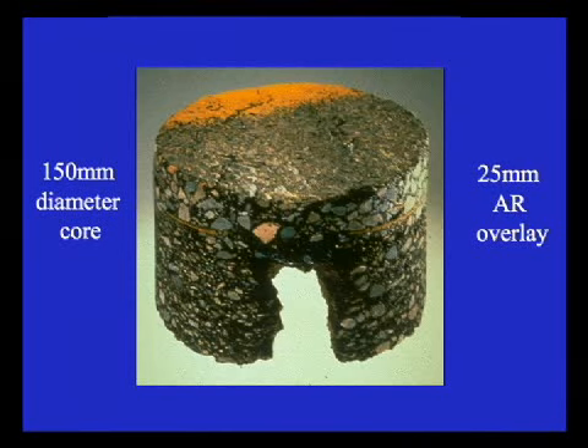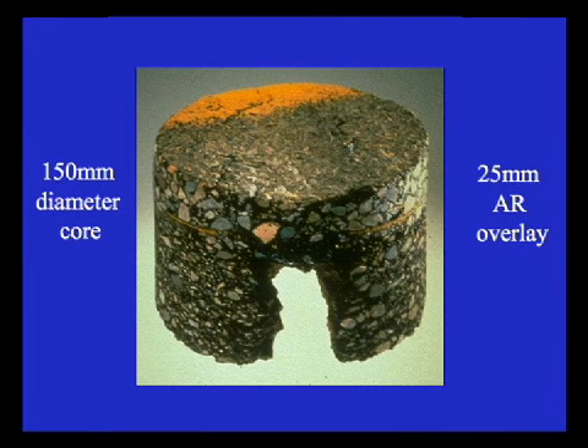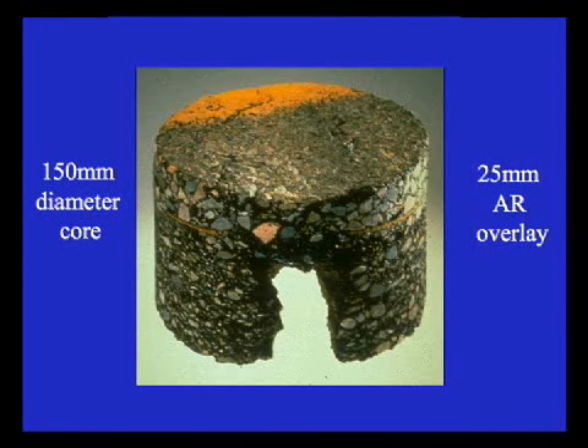I think you've seen this picture many times, but this core is still sitting in our Phoenix office, still intact. It just shows you how amazing the product is on a 25 millimeter overlay, and you can pick that up and it doesn't fall apart. It's just a really unique material. And if you look there, you can see that there appears to be a crack on both sides where the crack has reflected up through. A lot of times that's what you see in rubber.